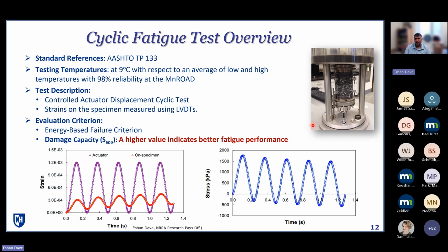And the testing is really done by using a cylindrical specimen, similar to a complex modulus specimen, that is glued on top and bottom and then imposed with cyclic loading. So you are applying a cyclic straining on that specimen and looking at how the capacity of the material degrades as you constantly apply a fixed amount of straining onto that specimen.